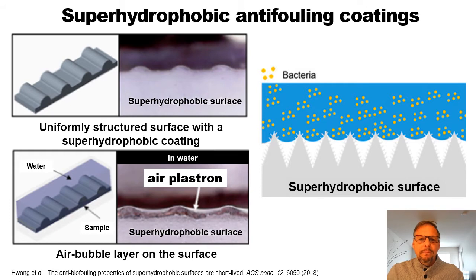So by doing that, maybe you can appreciate this a bit better in this slide. Here we have on the left some different molds where we have added water, and then air will be entrapped between the solid material and the liquid, in this case water, and these are called air plastrons. So pockets of air that are accessible to the liquid medium that is on top of it. And that's what you see on the right. In this case, we have the bacteria in yellow, water in blue, the hydrophobic surface in gray in the bottom, and in white, air that is entrapped, and that's the air that the microorganisms access to produce the cellulose at the interface between the hydrophobic surface and the water.